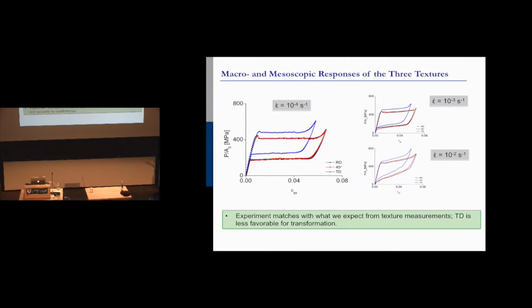So this is the 45 and the RD, and you can see that it doesn't take much stress to introduce transformation, and you get a lot of transformation. So those are pretty good. The transverse one, the one we cut like this, you have to pull really hard to get it to transform, and it ends really quickly. And so the experiment matched with what we expected from the texture measurements, and the transverse direction is going to be less favorable for transformation.